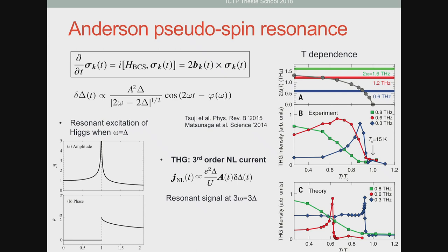So it's difficult, actually, to do these measurements at continuously tunable frequencies. So what these people did is they tuned the gap frequency by tuning the temperature. So if you assume that the gap frequency follows BCS temperature dependence, this is one way of tuning the gap amplitude. And what they show is that, indeed, the temperature at which the signal is resonant seems to match, at different frequencies, the temperature at which you would expect omega to match delta if it was to follow a BCS temperature dependence. OK, so far, so good.